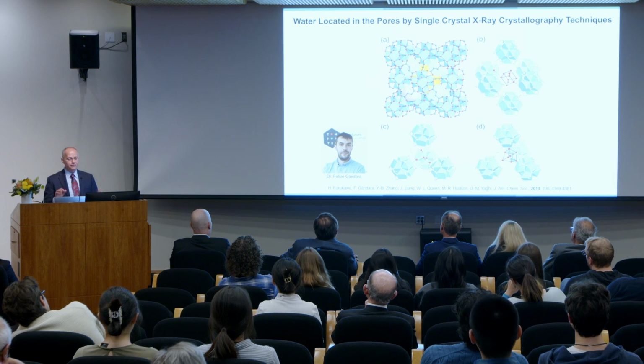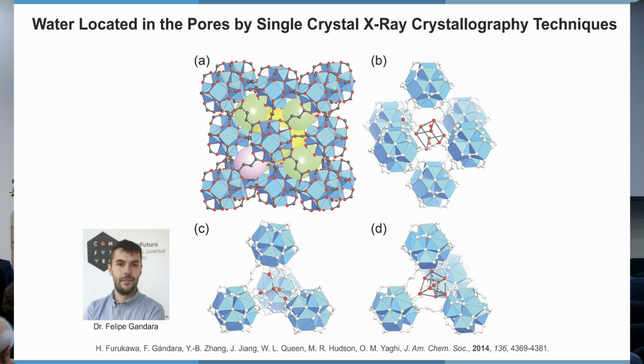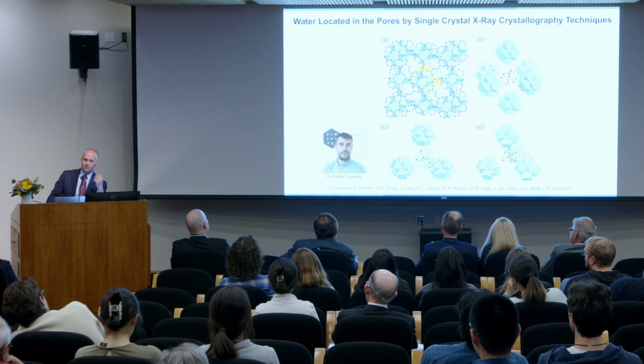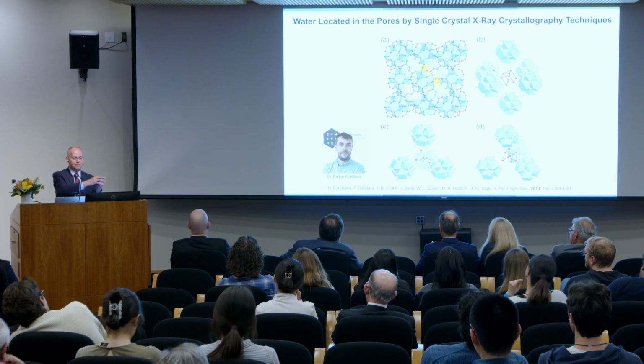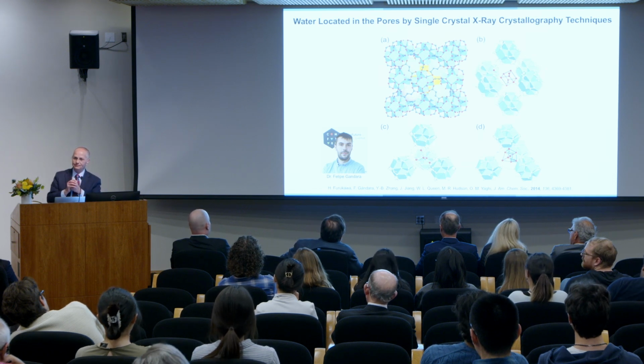And that's the beauty of working with crystalline material. That's what we have worked hard at in the last 25 years. And we found that those first water molecules that enter the pores go to the most hydrophilic sites and stay there. And because they're tightly bound by the most hydrophilic site, they don't come out. But what comes out are all the water molecules that bind to them. So in fact, these first water molecules were acting as seeds onto which water from the atmosphere was permeating through and binding through hydrogen bonds.